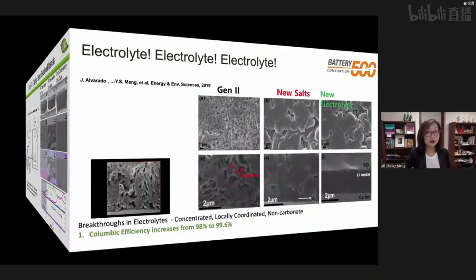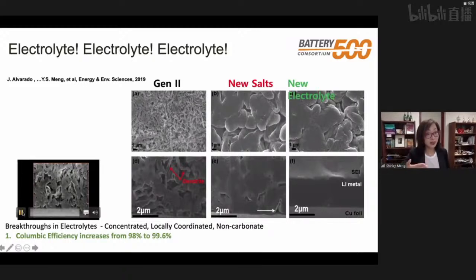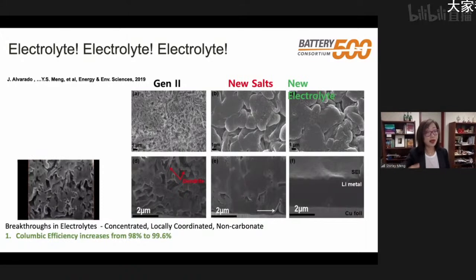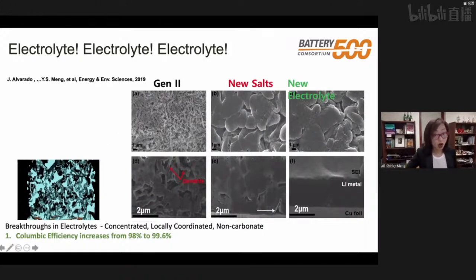So with this advanced tool, we can now cut lithium slice by slice in the FIB, and we can do three-dimensional reconstruction of electrochemically deposited lithium. In the electrolyte that scientists have been optimizing for graphite anode, carbonate electrolyte, we also call it the Gen 2 electrolyte, the morphology is terrible, okay? You can take the top view and the cross-section view and do the three-dimensional cut. It's really quite terrible. And the efficiency number is very low. So 98% means after a few 50 cycles, you have no capacity anymore.